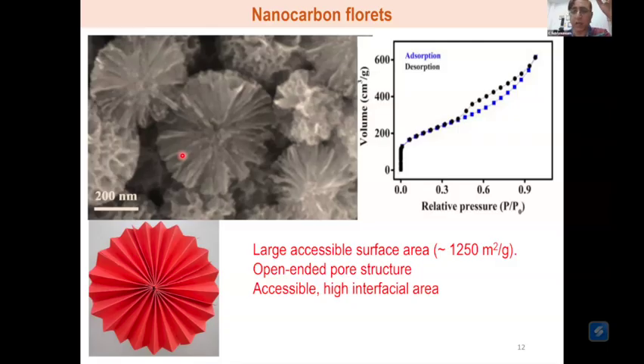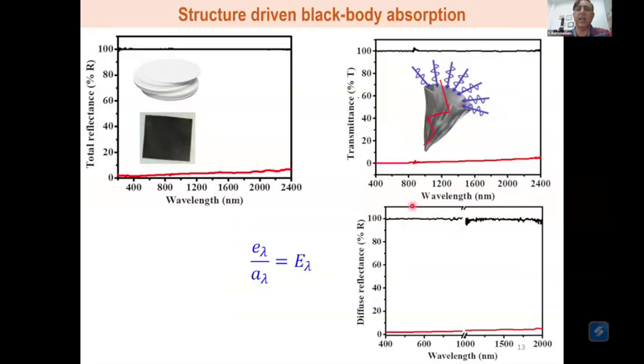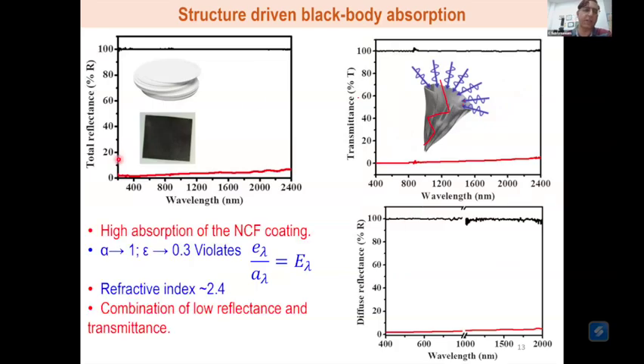And that is important, not only because it is manifested as a very high surface area of this material, about 1,200 meters squared per gram, but more importantly, this is what helps in its large absorption. Like I said, the reflection is almost next to nothing, transmission is nothing, and even the scattered component is very, very low across the entire spectrum. That means it absorbs the photons very efficiently.